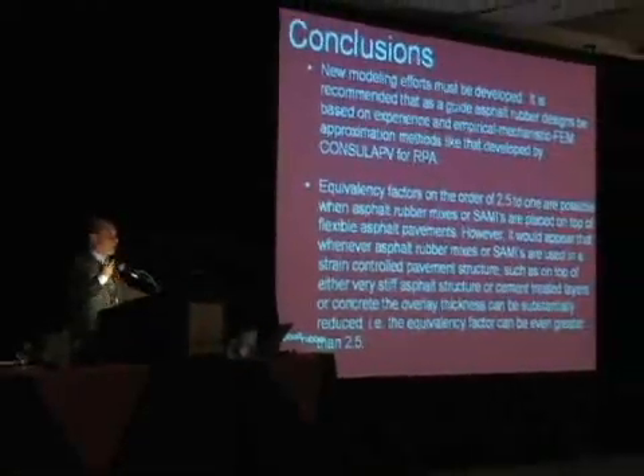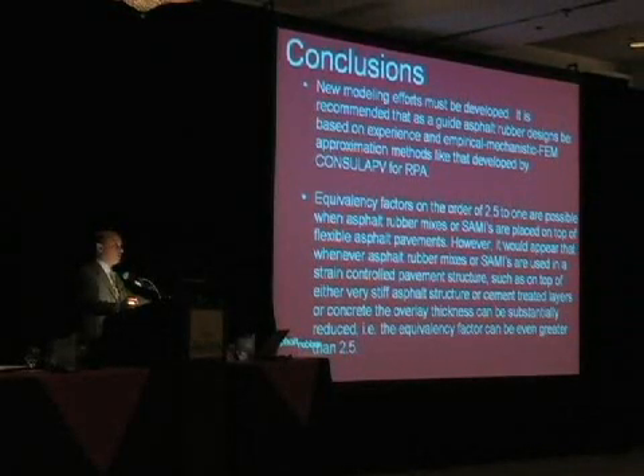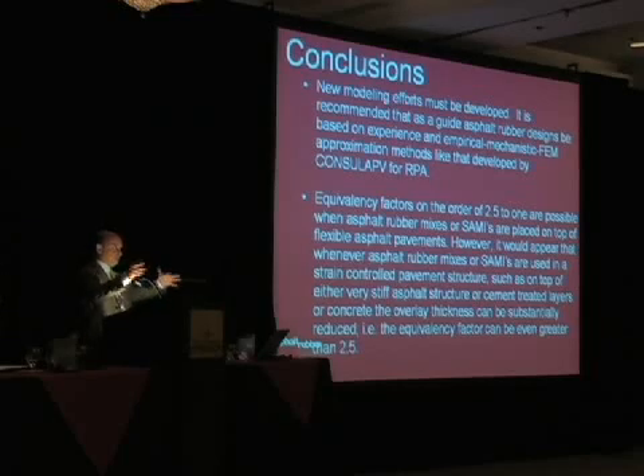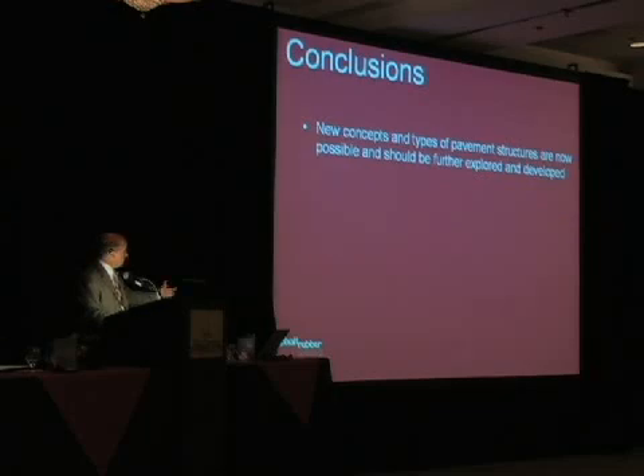And the equivalency factors are actually a function of how much in strain control a pavement is. I know this is deep now, but the more in strain control a mix is, the better asphalt rubber is. And the equivalency factors can go as high as 10, like in the laboratory reflective cracking tests that Caltrans has done. If you have pavements in those conditions, the overall benefit of having asphalt rubber is enhanced. And now, finally, new concepts can be considered using these eventually new design methods in which we control reflective cracking as a new design control.